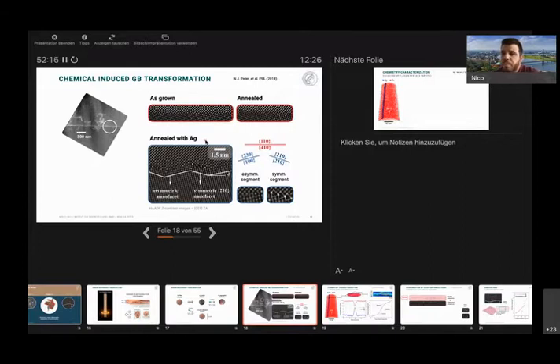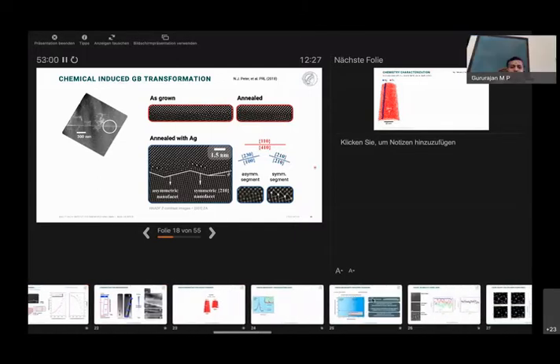Yeah, and 210 has a higher energy compared to 230, so it would prefer to have silver there to reduce its energy. Yes. So indeed, the faceting obviously increases the length of the boundary, which is first of all not wanted. But if it can take up more silver for the 210 facet, growing in length even more the more silver there is, then eventually it becomes again better to have the longer boundary, but broken up in several pieces that lower the energy further. And the MD simulations show this process of how this step moves, leading to the lengthening of these 210s.